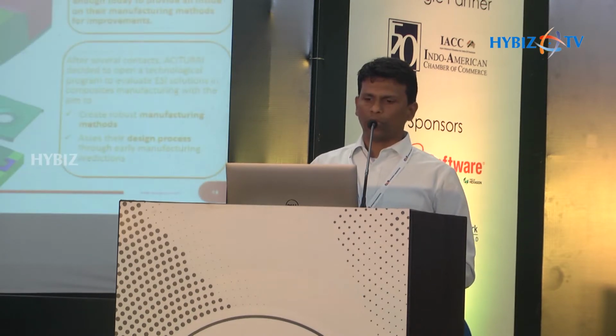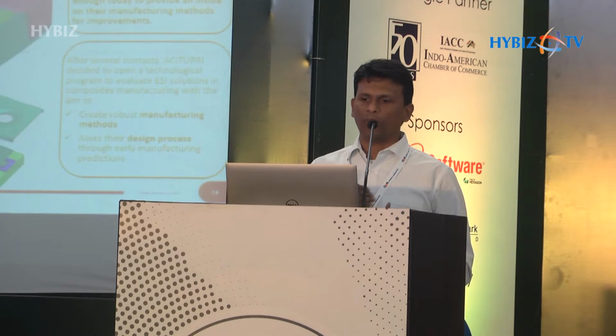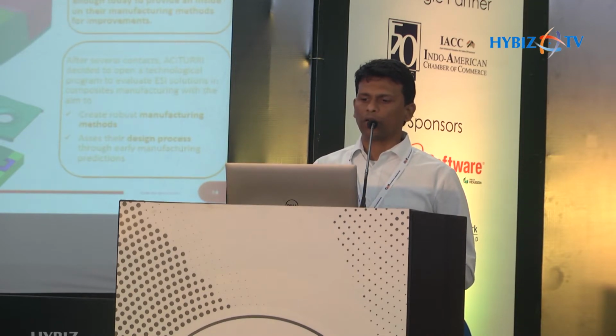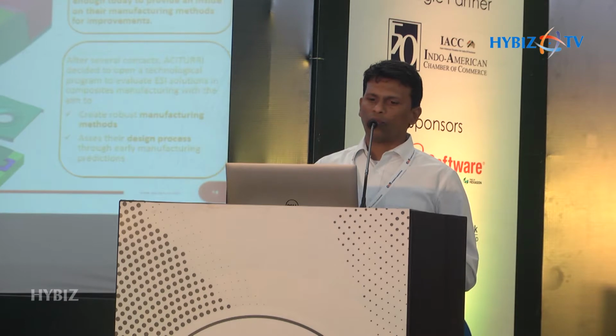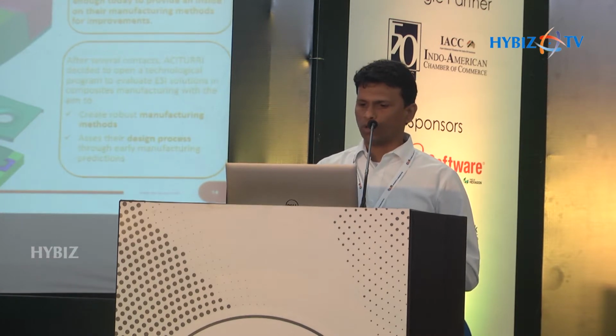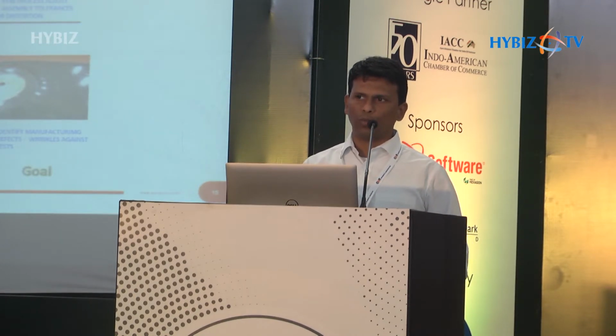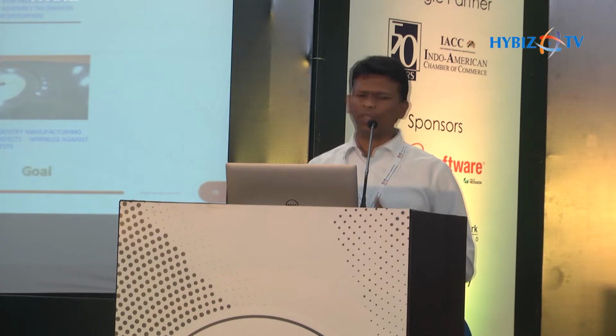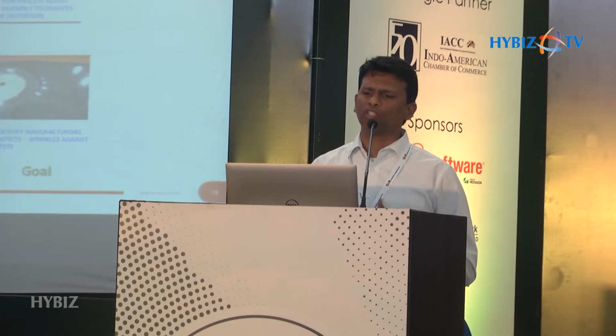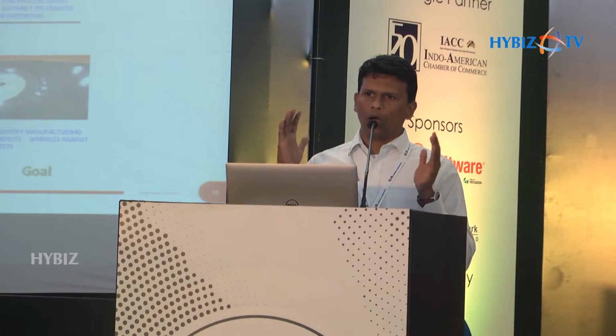A real-time example again with one of the customers, where the whole of this process was conducted to first understand the manufacturing behavior and also to create a robust manufacturing method for this section frame. What you could see here is a very interesting complete chain process, where they initially did the heating and then they actually did the vacuum forming. After doing the vacuum forming, they took it to the injection process, resin injection process. They did the RTM process, and then finally they understood what is the distortion that is coming on the part.